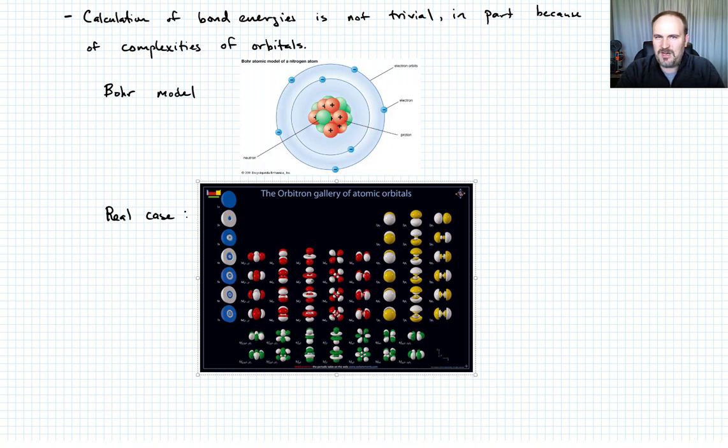So all the heat treating that you want to do to a steel and the cold working that you might want to do to make it stronger, which we'll talk about in this class, all of those efforts can do things to change the strength, but you'll never change the modulus. The reason is that in all of those things, you're not actually changing the atomic bonds themselves. You're just changing the arrangement of groups of atoms, but the bonding remains the same.